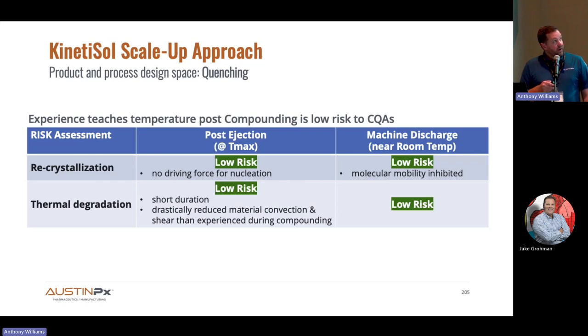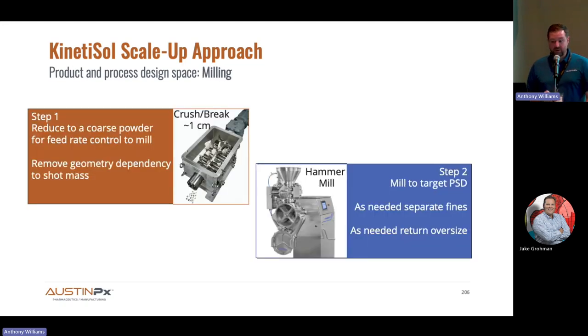And so at a hot temperature, there's no driving force for nucleation because we're above the T critical. I'm going to factor these terms in. But then, when we get it down to low temperature, we vitrify the dispersion. There's no molecular mobility. If you have a risk right here, you have chosen the wrong process, and you should go somewhere else. You should not be here. But this is really, again, we're talking about seconds of exposure. There's a practical perspective here. This is just a low risk process.